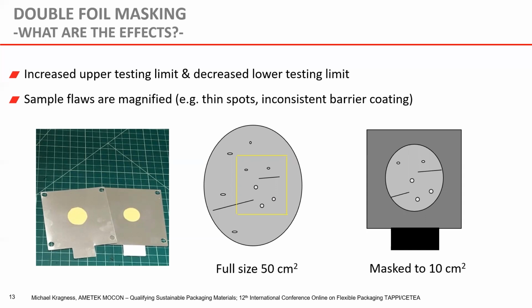Now what that's going to do is increase the upper testing limit by 5 times because we're masking down 5 times. So for example, if you have a coated paper that's about 200 cc's per meter squared per day in transmission rate, and you have a full-size sample and the instrument can only go up to 100 cc's per meter squared, you're going to have an issue. It's going to overrange your instrument. But when you mask it, you're allowing that instrument to now have an upper limit of 500 cc's per meter squared per day. So then you would be able to get data on your material that's around 200 cc's per meter squared per day.